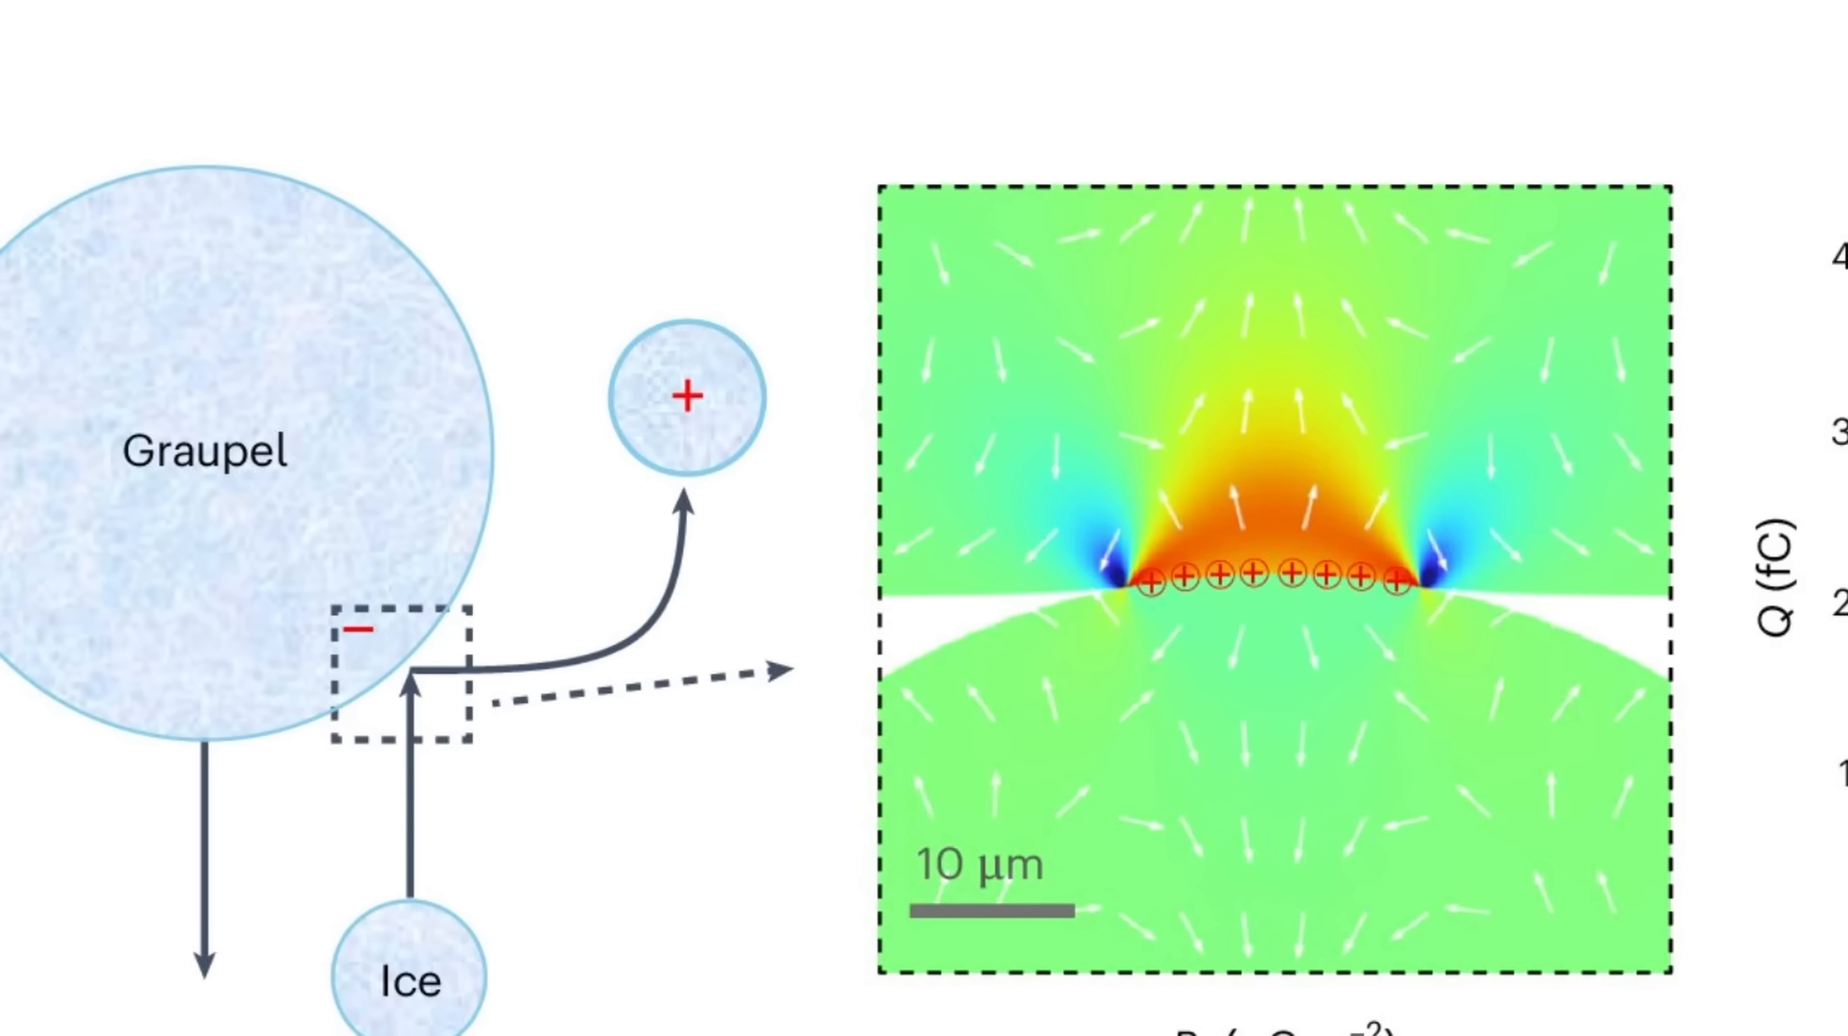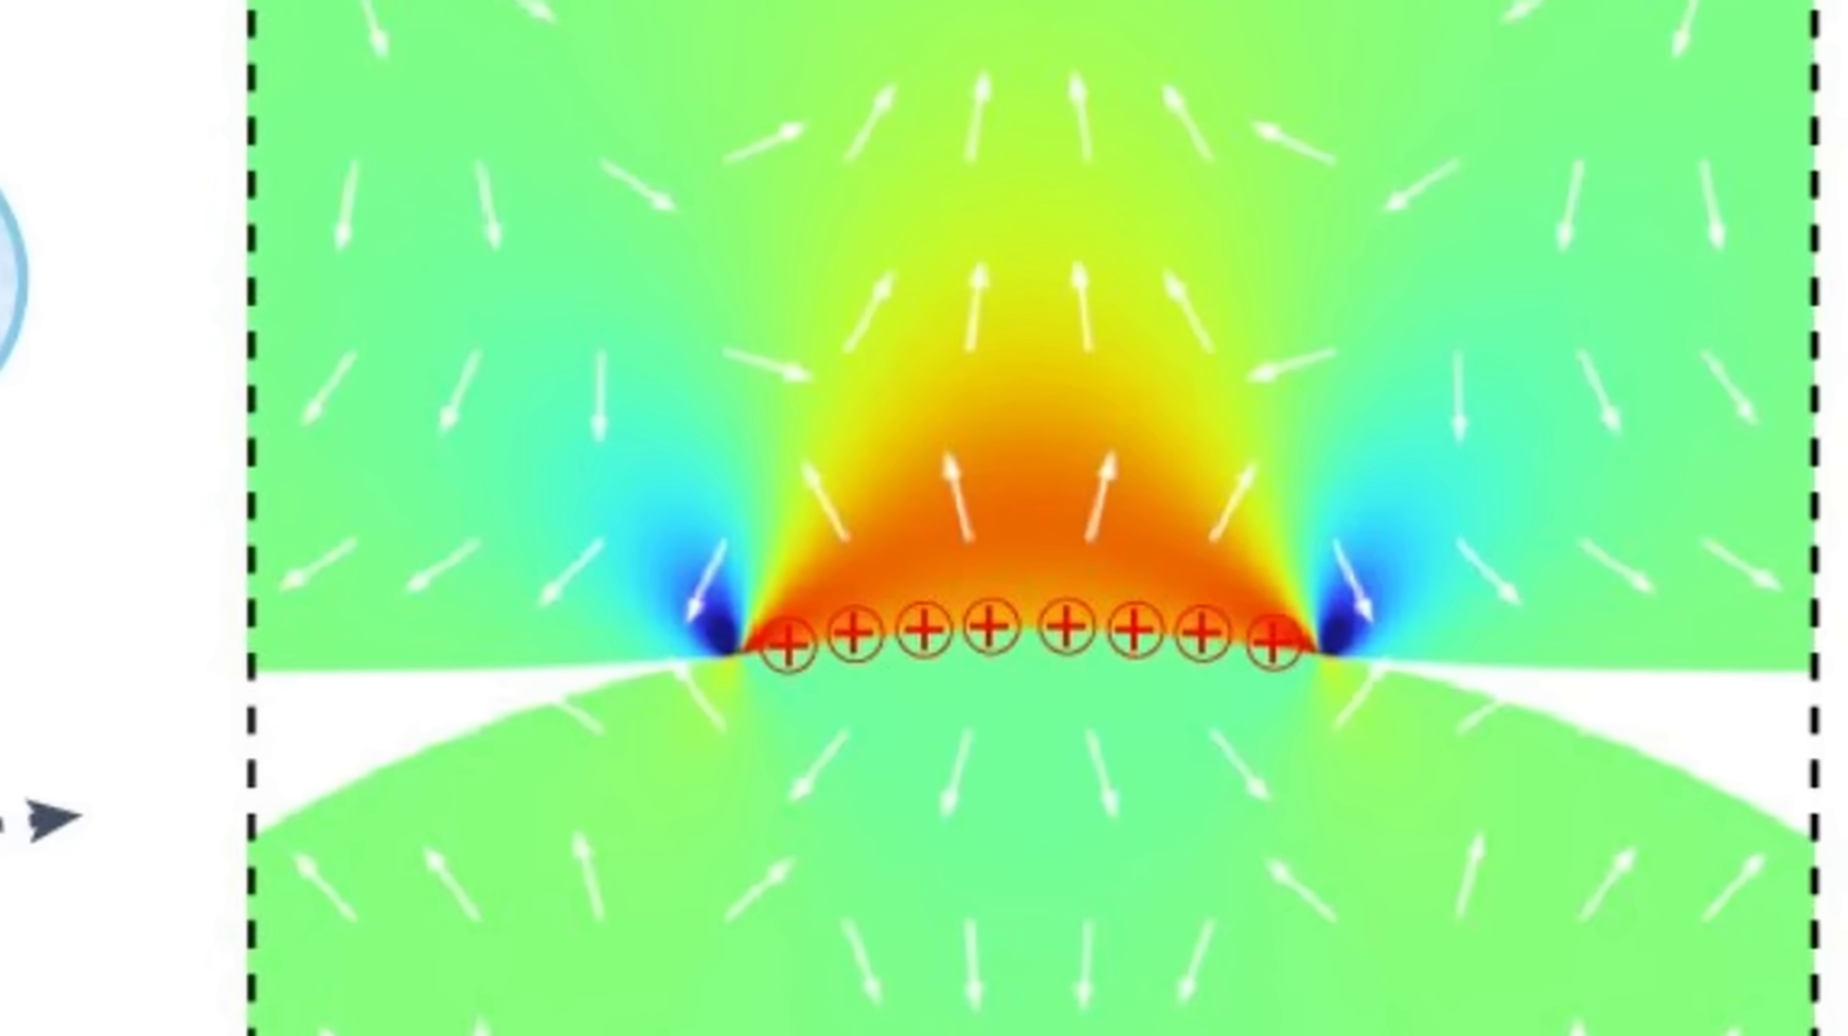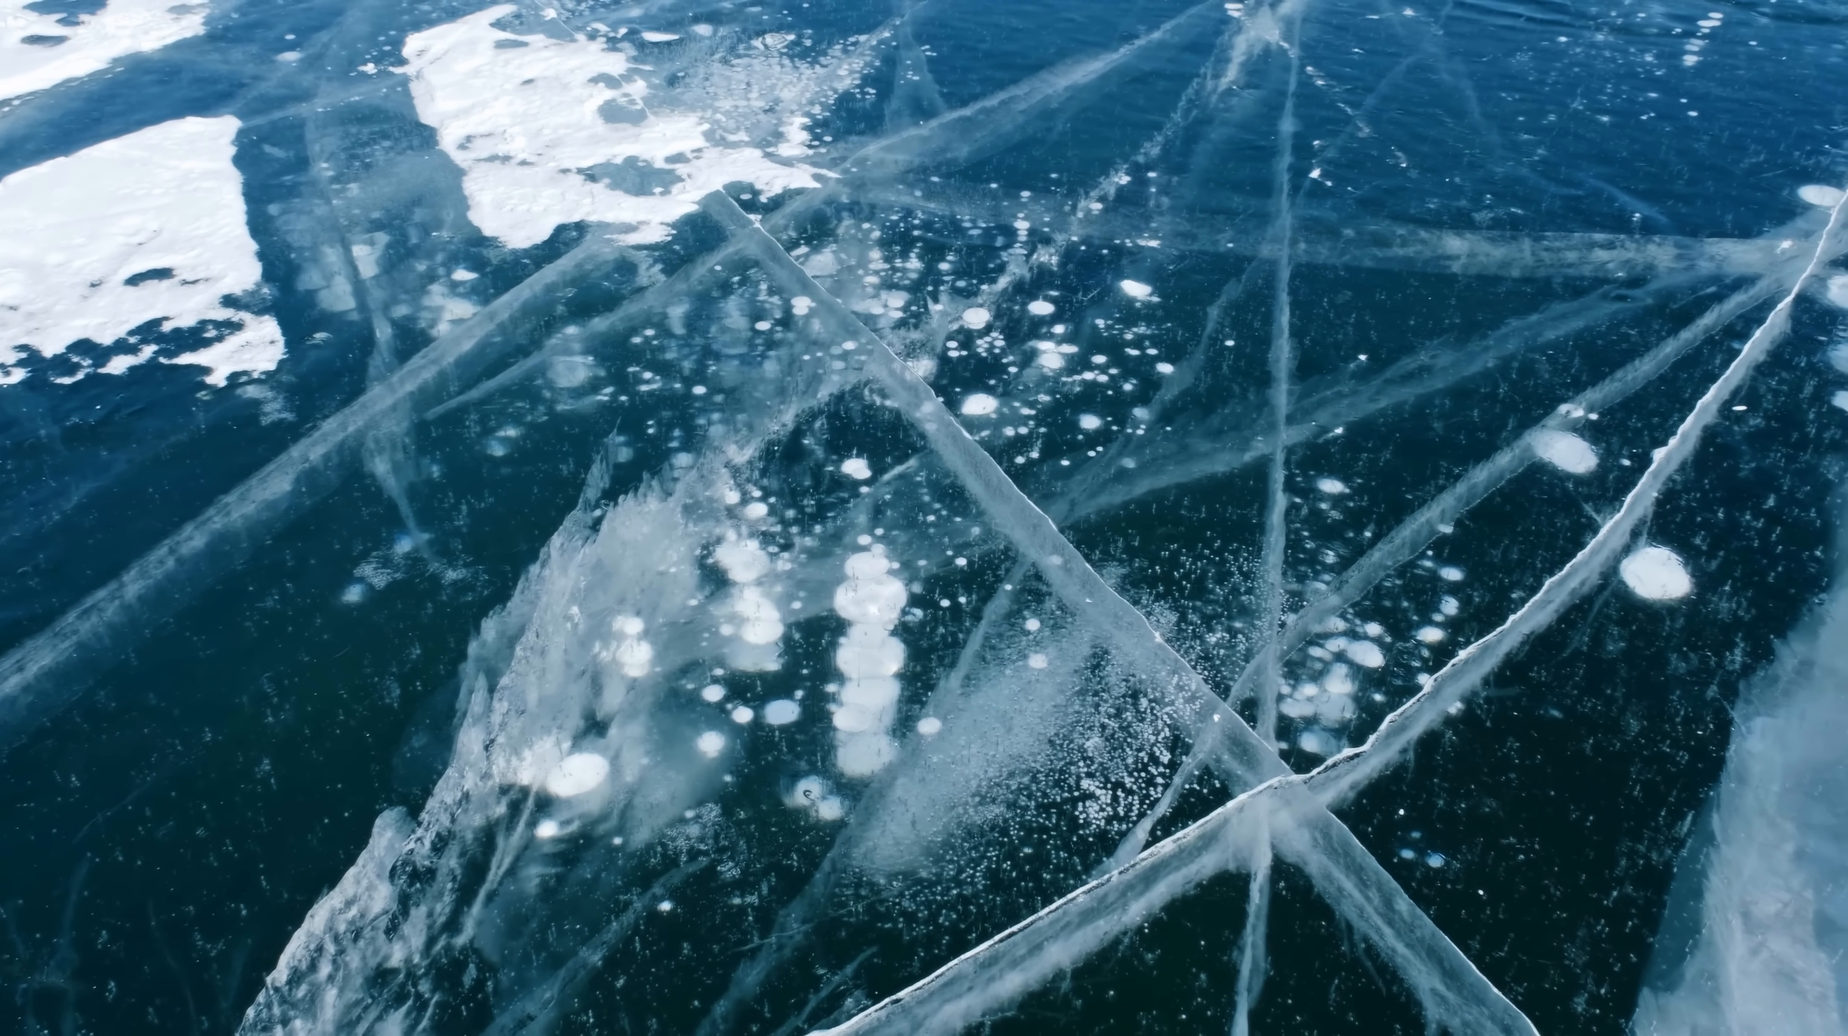And this has now been demonstrated by preparing so-called ice capacitors, or layers of ultra-pure ice frozen between two gold-coated aluminum electrodes where the charge was then measured by using a very specific tool. And so here by applying an oscillating three-point bending deformation, researchers were able to precisely measure the applied bending and the resulting electrical charge, which allowed them to calculate the flexoelectric coefficient for these pure ice particles. And what they discovered was quite remarkable.